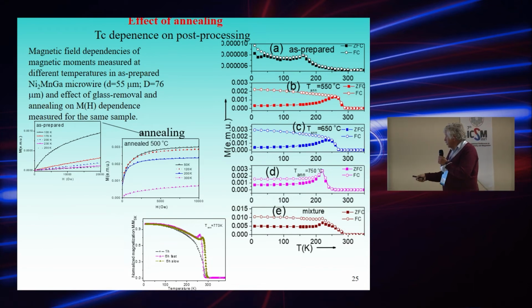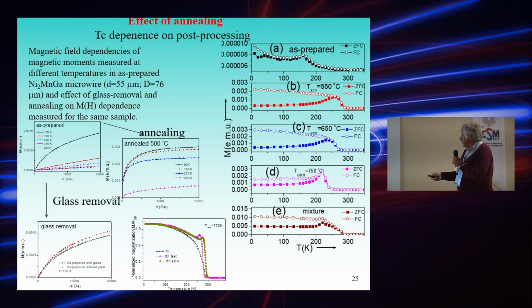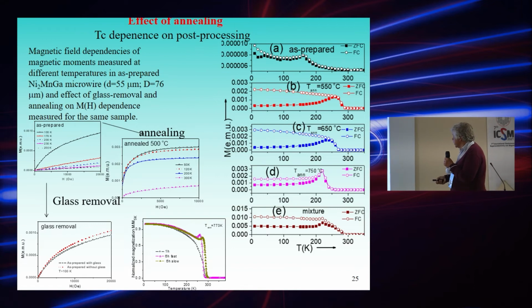And also another feature is that after annealing, all these materials present saturation. Without annealing, it was not. And this effect of glass removal on the magnetization curve was remarkable, but not very big.